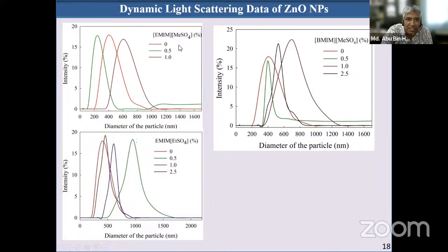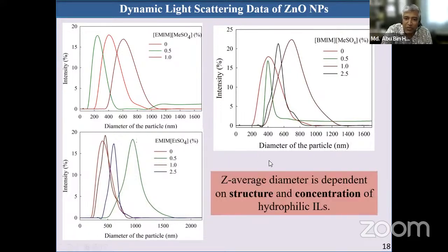This is dependent on, this 0 means no ionic liquid, and we have changed the concentration. This is one ionic liquid, this is another, this is another. So actually we have seen that the Z average diameter is dependent on the structure and concentration of hydrophilic ionic liquids. So this is DLS, and actually this is the hydrodynamic diameter.